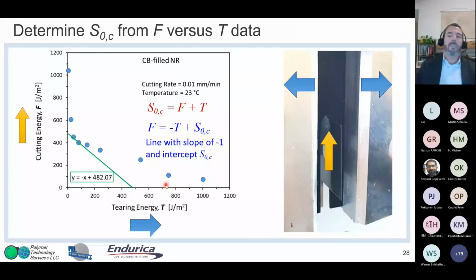So as I mentioned, it's a series of measurements. So you open up the crack at different levels, and then you very slowly push the blade in. We also make measurements at other faster rates first, and then slow down to this final very slow cutting rate, and for which the data is shown here. So you can see these data points here are collected at very low crack openings.